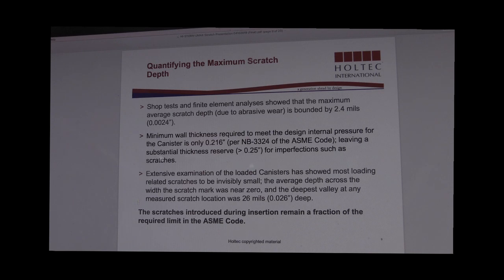So, continuing what I was just saying a moment ago, when we look at our shop test results as well as our numerical predictions and finite element analyses, we see consistency between them, that the maximum average scratch depth, which is more of a measure of abrasive wear, is bounded by 2.4 mils, 0.0024 inches. And to put that into context, the minimum required wall thickness to meet the design internal pressure for our canister, which is 100 PSIG, the minimum required thickness to resist just that internal pressure load is 0.216 inches.